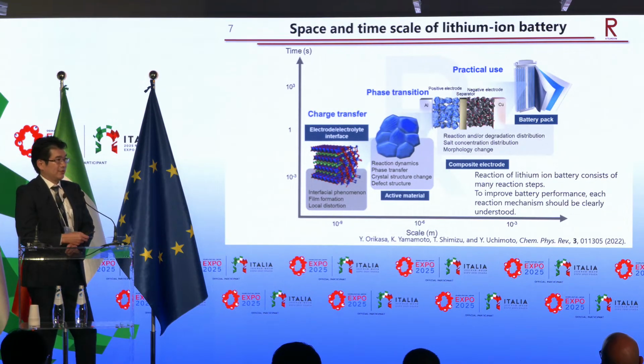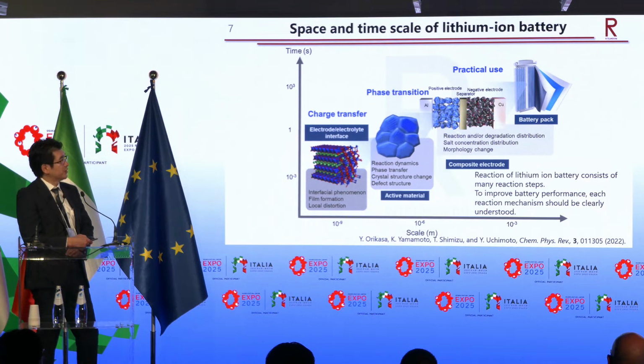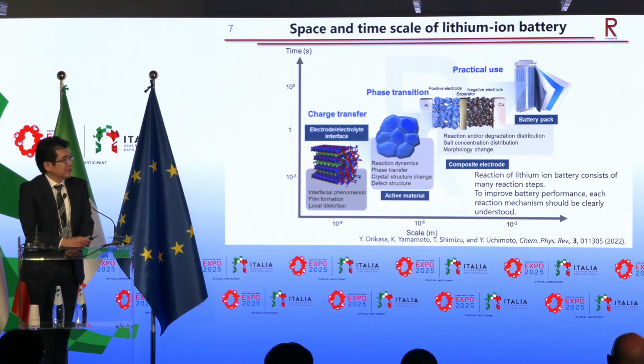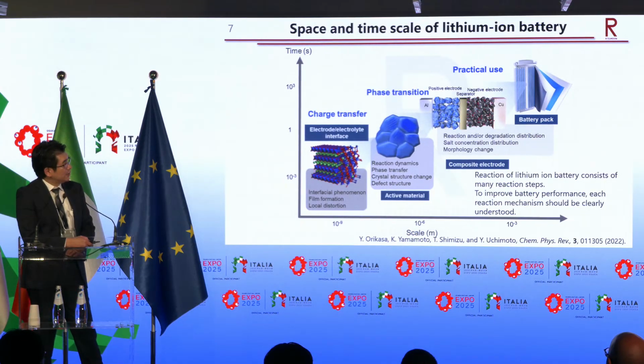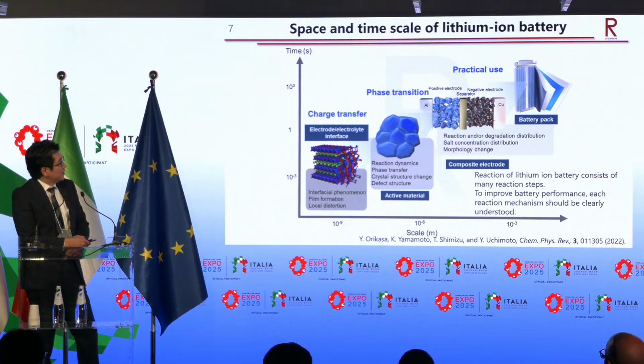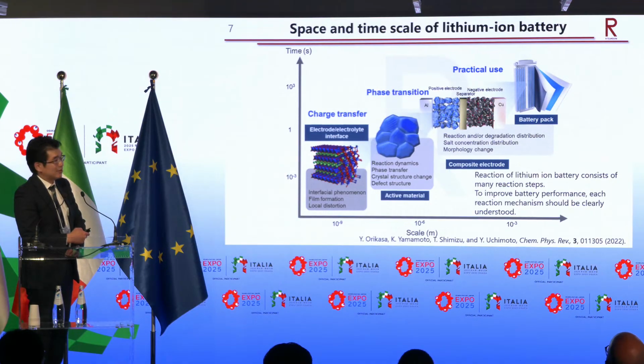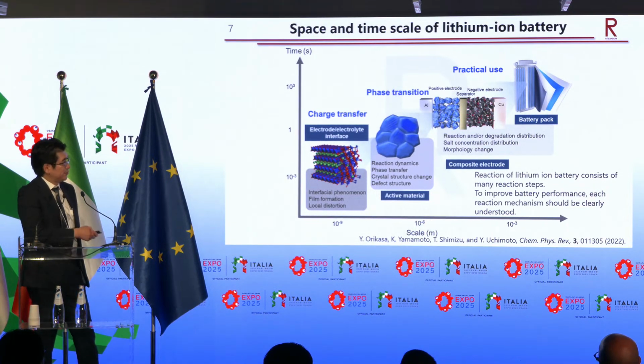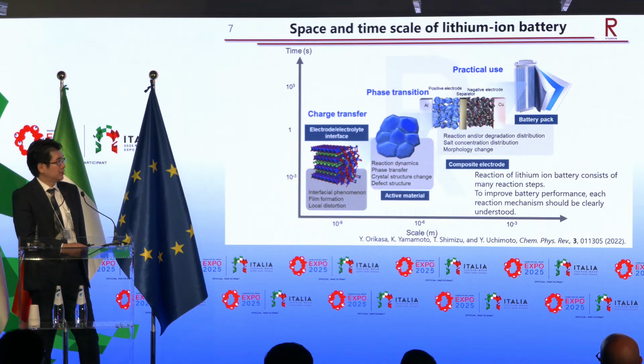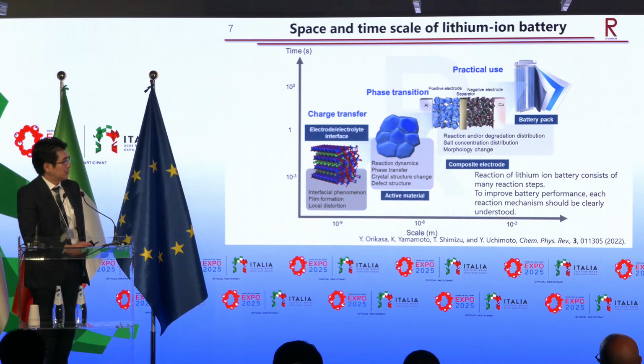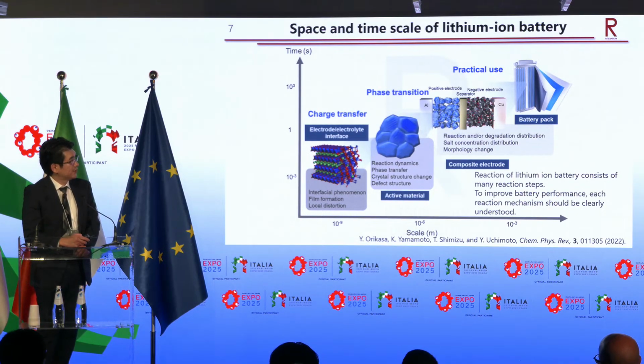But only 1 micrometer of material cannot store enough ions for real battery operation. So we need to make a 3-dimensional structure using composite electrode, as shown here. The thickness of the electrode is about 100 micrometer, and for the battery pack, the scale is about centimeter. And the reaction time is also minutes or 1 hour scale. So to improve the battery reaction, we need to consider every elemental reaction, because if some reaction stops, all reaction cannot be achieved. So also we need to analyze all elemental reactions based on the electrochemistry.